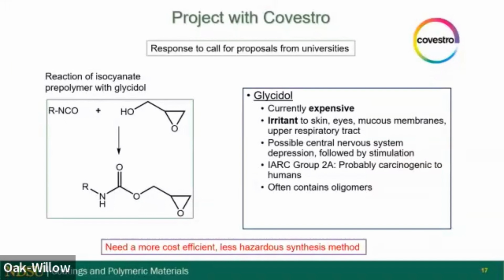Later on, Covestro actually had a call for proposals from universities for different projects. And so we responded to that because we had worked on this epoxy functional polyurethane chemistry. And the way we make this is we react an isocyanate with glycidol to make the epoxy functional polyurethane. But one of the barriers to scaling this up was the cost of glycidol. Very, very expensive raw material, but it's also a bit hazardous. And so you have to really handle it under very strict conditions. And so we really wanted to come up with a more cost-efficient way to make this epoxy functional polyurethane. And of course, Covestro in the polyurethane business was interested in funding our project.